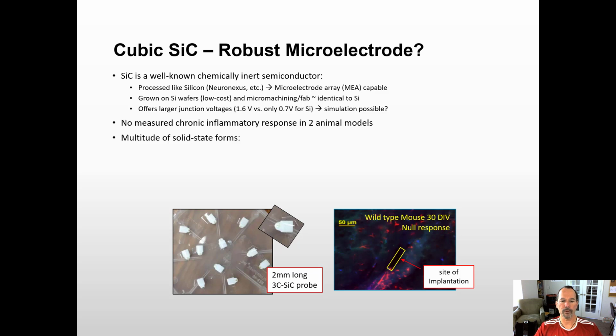I'd like to point out, for those of you not familiar with silicon carbide, it's not just vanilla silicon. There are multiple solid-state forms of silicon carbide. It can be both polycrystalline and amorphous. The amorphous material is what you hear a lot about. Well, they're talking about this amorphous coating. It's an excellent electrical insulator. It can be put down conformally using PECVD typically, and it's been used to enhance the lifetime of many other devices made with polyimide and so on.